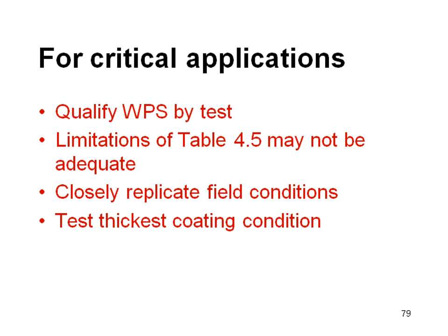Now, AWS has a Table 4.5, which has the title Limitation of Variables. The production welding need not be identical to the test conditions. As an example, if you run a test on 1-inch plate, should you be able to weld on 1-and-1/8-inch plate in the field? Well, that's probably within the limitation of variables. You run a test on a 1-inch plate, should you be able to go to 4-inch plate? Well, maybe that's too big of an expansion. That's the point behind Table 4.5. It defines those limits.